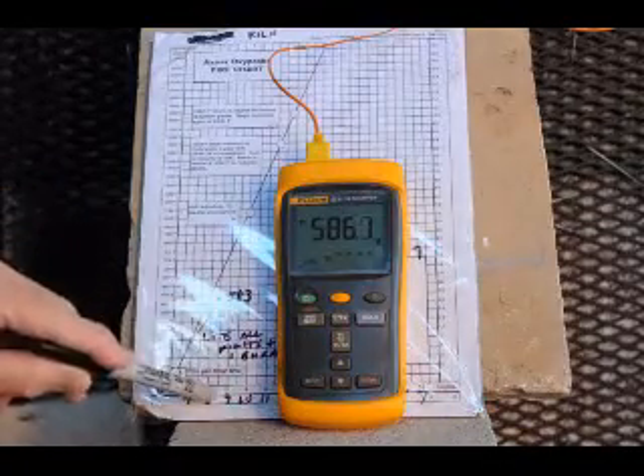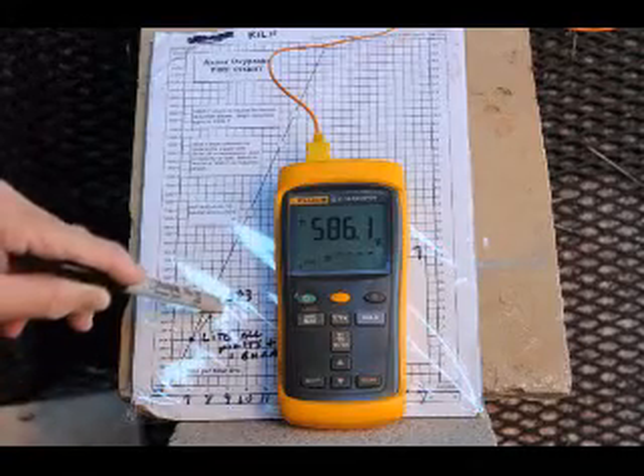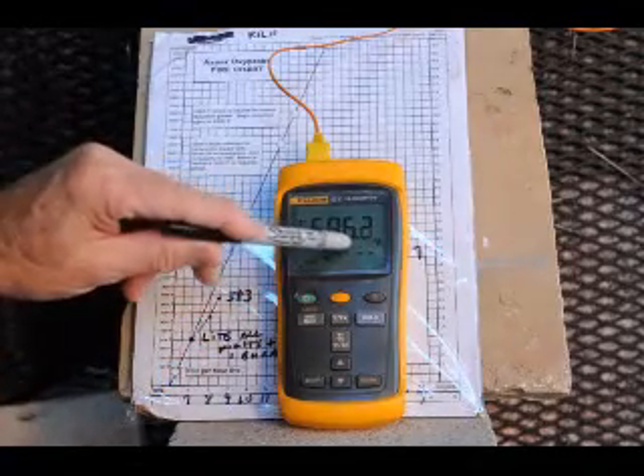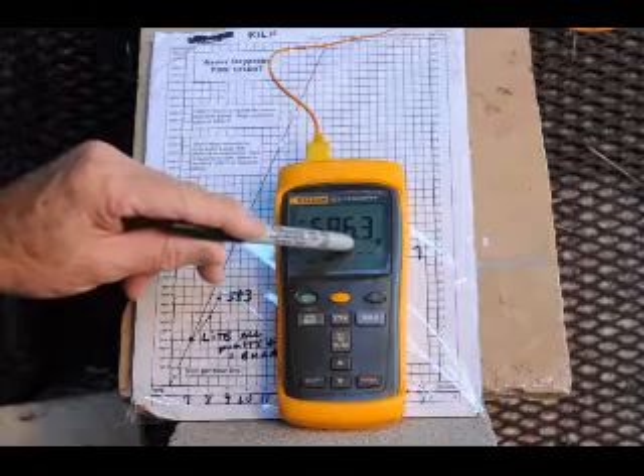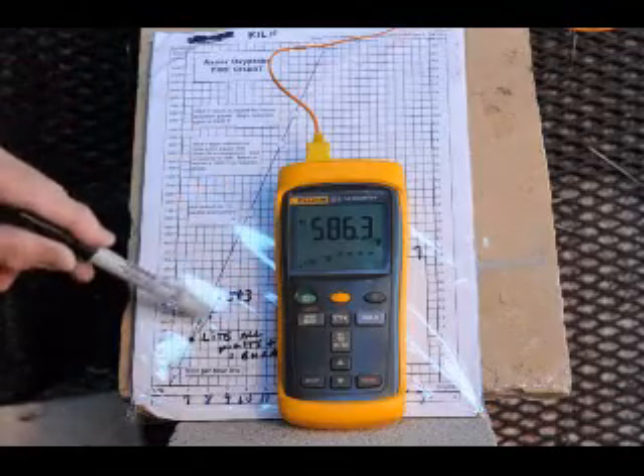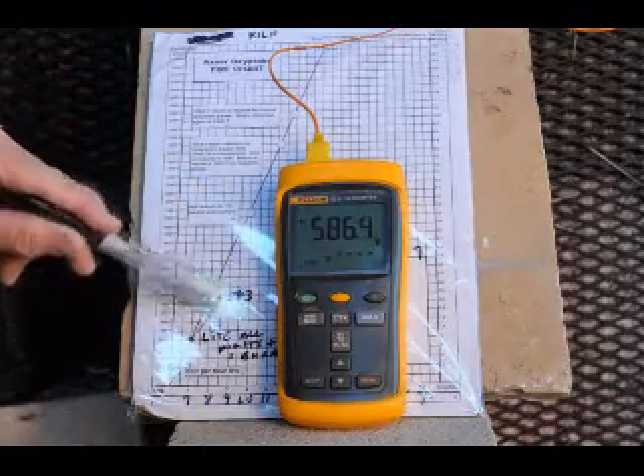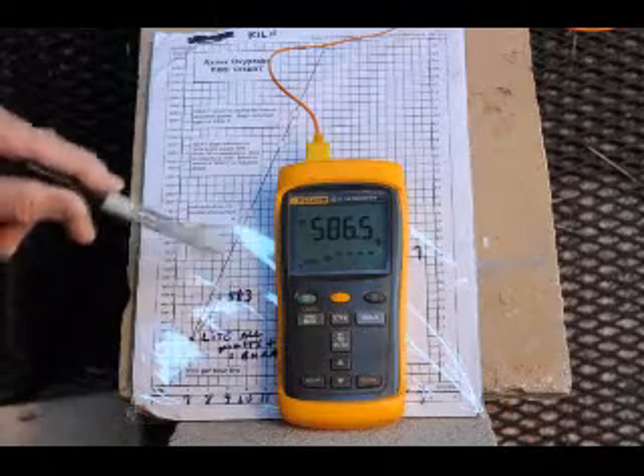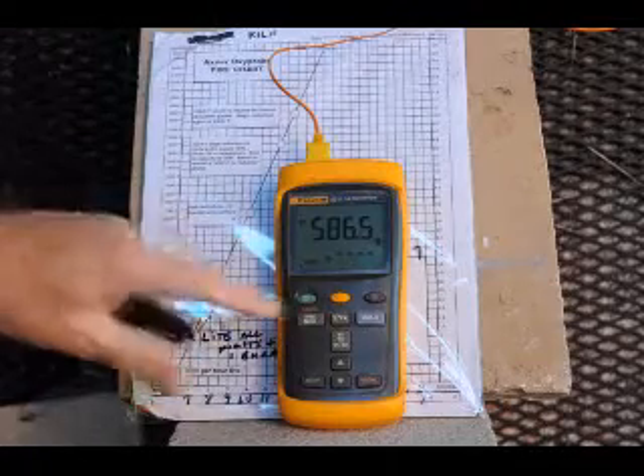It's now 8:30. Temperature is 583. You can see the temperature rise has slowed down a good bit, but in the past 30 minutes it did rise at 300 degrees an hour, which is this line right here. So I'm going to light 1 more burner.